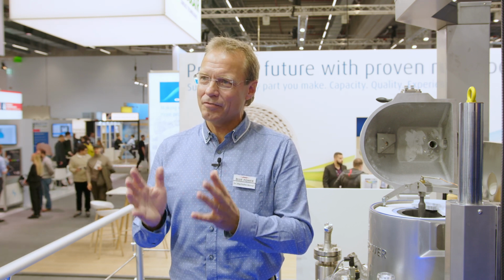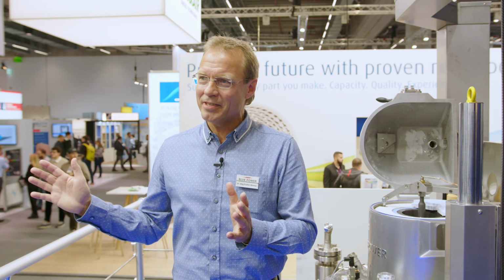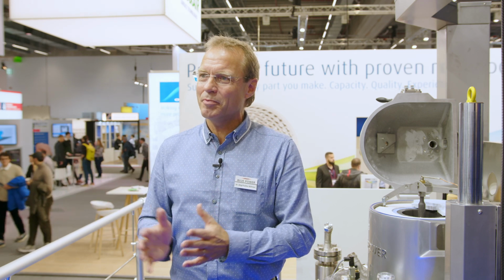The longest experience and history we have with gas atomizers. Gas atomization has the potential to create spherical powders in very different size ranges by varying process parameters. And with the ultrasonic systems, we are a little bit more limited with the parameters that we can vary. We can create also very, very spherical particles.